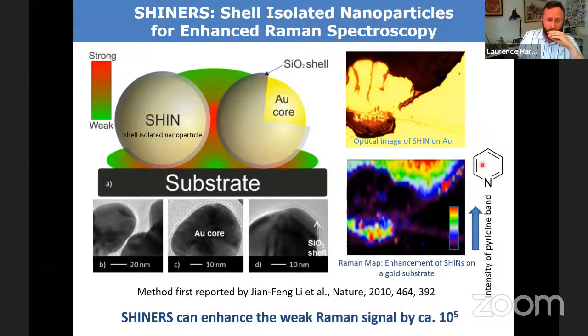And when we put pyridine, there's a band just above 1,000 wavenumbers, and it's from the adsorbed pyridine. And where we have these particles, there's a very nice correlation of the signal enhancement of this adsorbed band of the pyridine.